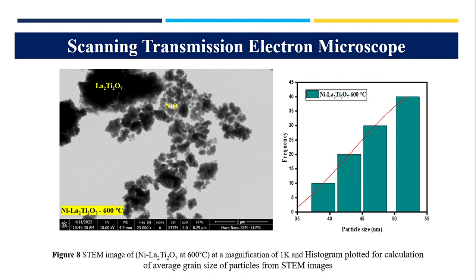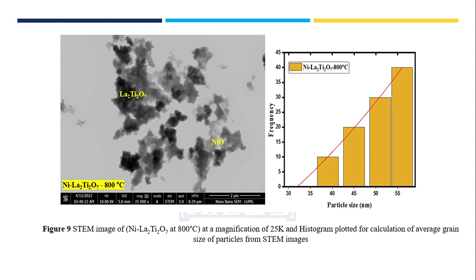There is another characterization technique, which is STEM. It is used to find the particle size of the material. As you can see in the picture, the large or darker area in the image shows the lanthanum titanate, whereas the lighter part shows the nickel oxide, and the average particle size of the nickel loaded lanthanum titanate that was observed is 40 to 60 nanometers. This is also the STEM image of the nickel loaded lanthanum titanate at 800 degrees Celsius, at a magnification of 25K.